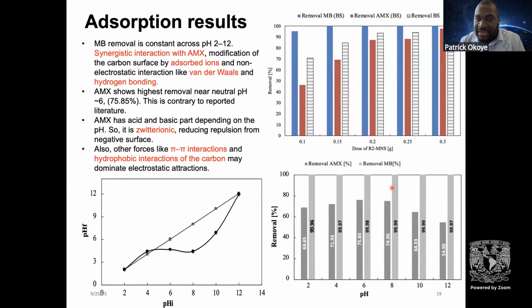But then with amoxicillin, we also have a very strange concept. At near neutral pH, our amoxicillin gives us our best result. This is in part because amoxicillin is, they call it, amphoteric. So it does have a positive and negative part, that is acidic or basic part, depending on the pH. So in the solution, where it is near neutral pH, they call it the zwitterionic effect, which helps to reduce repulsion from the negative surface. Also, we can have forces like pi-pi interactions and hydrophobic interactions of the carbon, which may dominate electrostatic interaction. And this is quite new in this field. We have actually laid these things down and tried to explain why these things happen in this way.